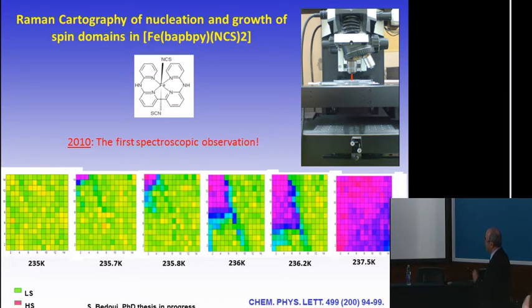When you increase your temperature here, you see the appearance of the high spin form here. And as you continue, you see the domain of the high spin form increasing till reaching all the crystal. So by Raman spectroscopy, we could demonstrate that the spin crossover phenomenon on the crystal behaves as a nucleation and growth phenomenon. And then we wanted to check if we can follow this optically. This is the same crystal through crossed polarizers, and we wanted to see if we can see the switching optically.